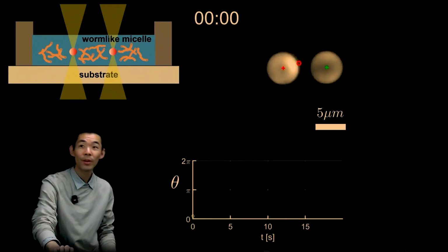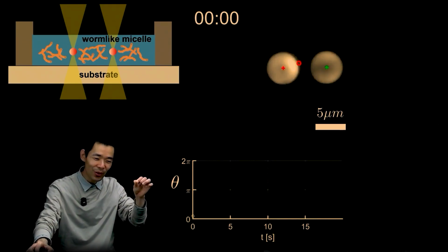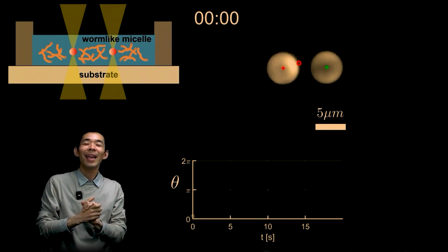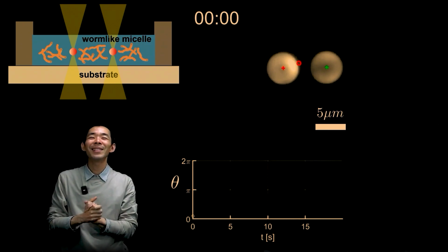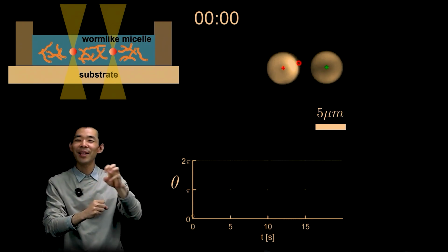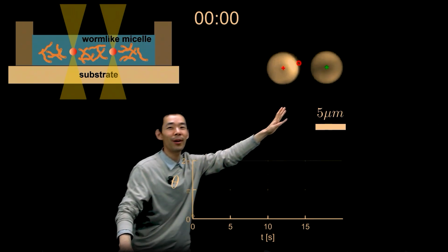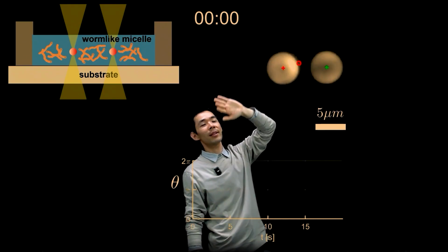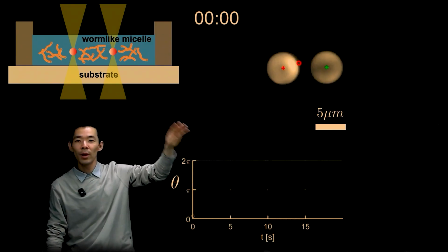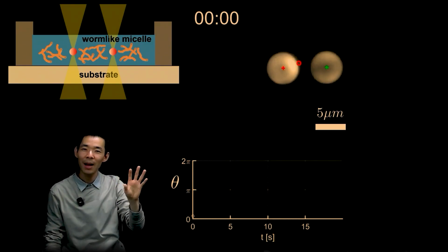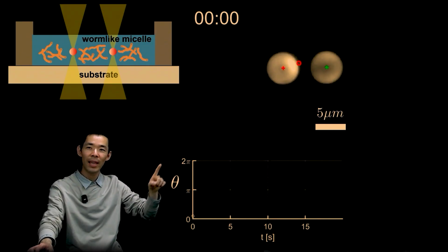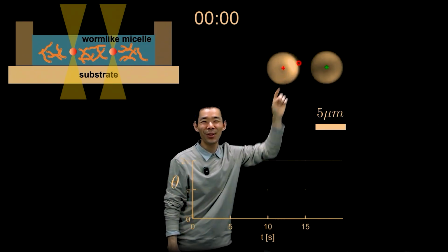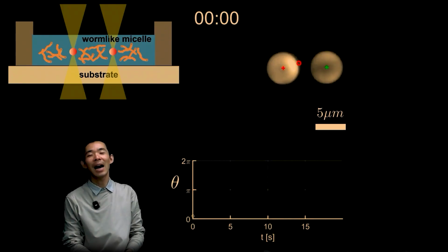So we can do this experiment where you have this viscoelastic worm-like micellar solution contained inside the solution. And what we're going to do is to do a relaxation experiment where we have this outer particle, located by this green cross, suddenly translating around, and it's going to do several rotations and then suddenly stop at the end. We're going to keep track of the angle of the center particle, as you can see located here with the red circle, and plot that as a function of time.